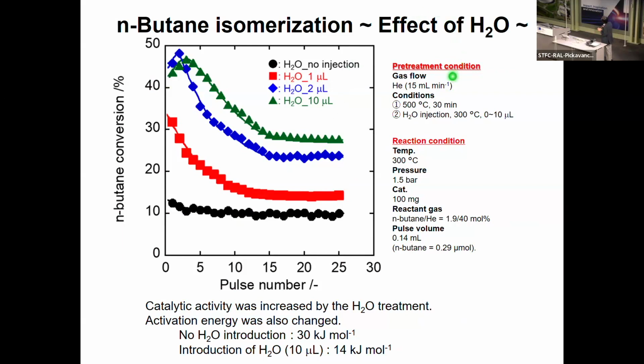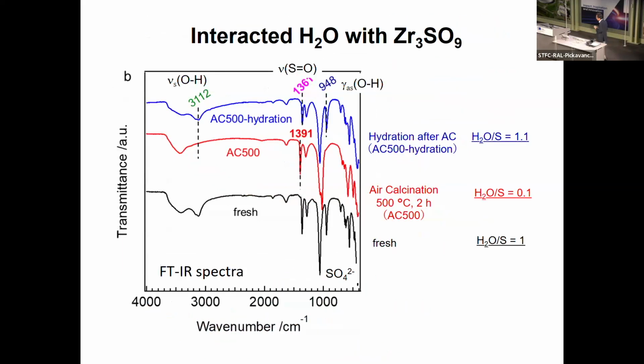Just after the high temperature calcination, this material shows some activity because some amount of water can be dissolved on the surface. But if you add more water on it, then you can have higher conversions of n-butane isomerization reactions. So the water is playing some important role in the course of these reactions. Very simple analysis.